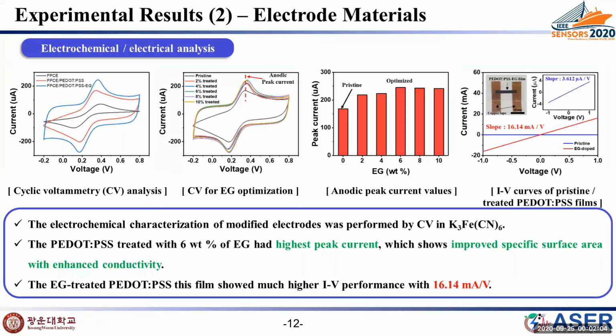Electrochemical characterization of the modified electrodes was performed by cyclic voltammetry in ferricyanide solution. The conductive polymer on carbon showed a great redox peak. Moreover, modified electrodes with ethylene glycol treated PEDOT:PSS showed a higher peak current. This means EG-treated PEDOT:PSS has better charge transfer property with larger surface area than the pristine one.